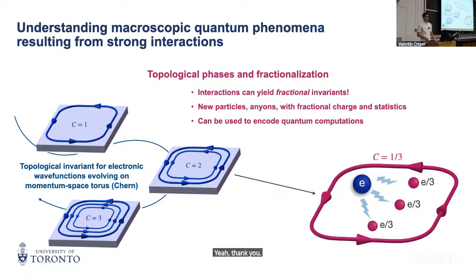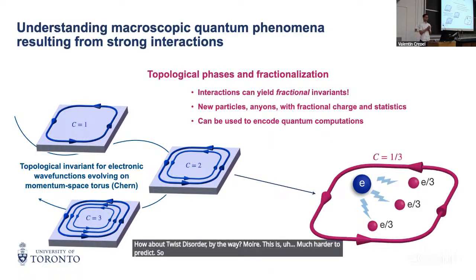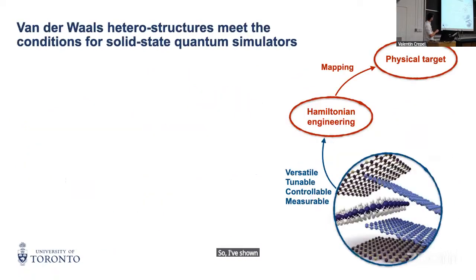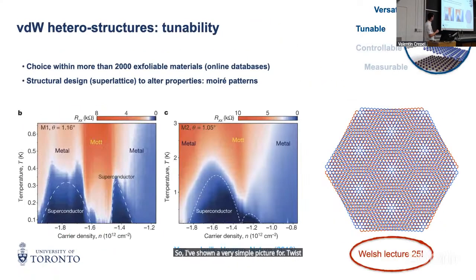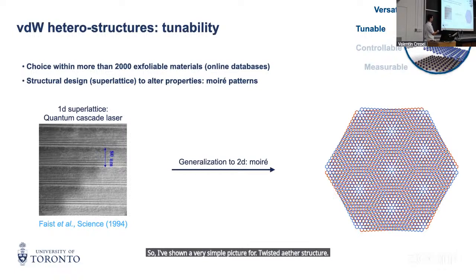Other questions? How about twist disorder, by the way? Moire disorder. Oh yeah, this is much harder to predict. So the twist disorder is because, I've shown a very simple picture for twisted heterostructure. What usually happens is that the atoms prefer one of these special stacking configurations and will just form disorder in twisting to have a bigger size of that stacking configuration in that bilayer.